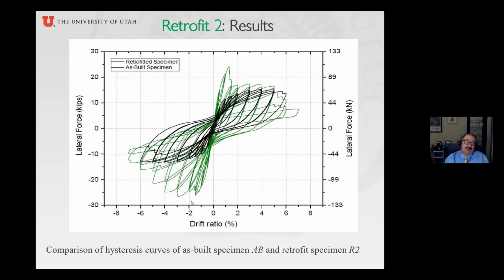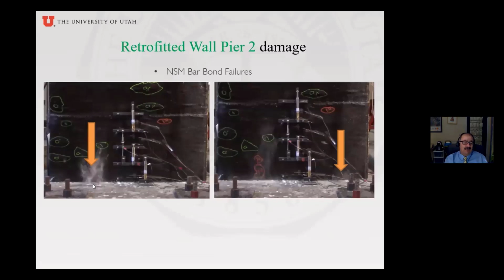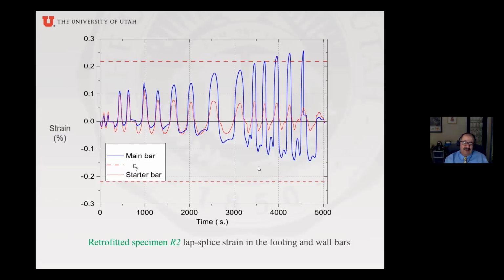On the other hand, the other side of the wall did just fine, because in that case the anchors were actually packed correctly, and you can see we achieved our goal. And here we saw it in the video. You can see here that the resin pulled out from the concrete. It didn't bond very well to the concrete in the hole, and we got these dust clouds that came out. And you can tell it's because we didn't break the rod. The rod is very hard to break, but the rod did pull out from the hole because the resin in the hole was not packed properly. And again, here you can see that the lap splice did very well actually in this case. It's almost like it didn't matter.